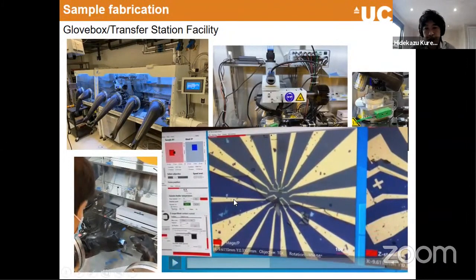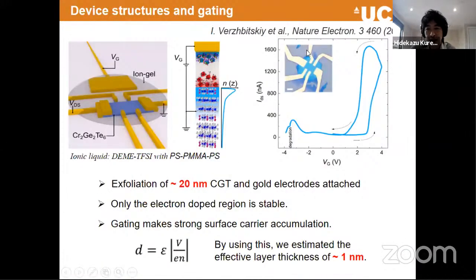Okay, so if you're doing a good job, we can nicely place the thin film within the bar or electrode. Then we can do some transport experiments. And this is just a schematic of this. We have an electric contact, and this is CGT about 20 nanometers for this particular experiment. And then we put on the ionic gel and then gate on the side.